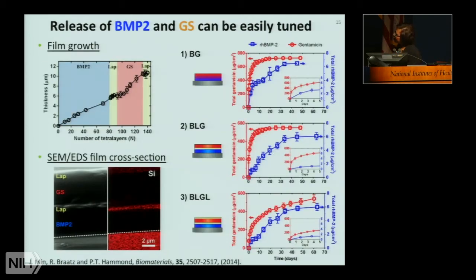On the left, what you can see is the thickness in the film as Juha built up differing numbers of BMP2 layers. Then she introduced these ultrathin laponite layers, then gentamicin sulfate, and then in some cases she capped that off with another laponite layer. The question was whether we could segregate the 2 drugs into compartments. And here you can see with electron microscopy and a method called EDS that these dark regions are the drug-containing layers. These bright regions are the laponite capping and intermediary layers that separate them. Here we can see red as the silicon-containing layers. These are the clays that are essentially separating our materials. When we look at the release between these different systems, with just the BMP2 and gentamicin sulfate, we get some nice results.